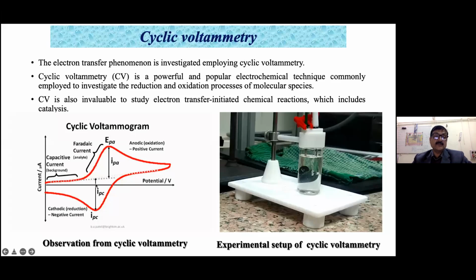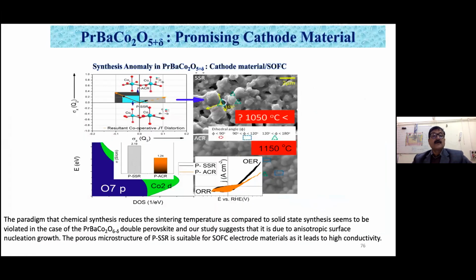There is a peak on the negative side, which is the cathodic reaction. This is the anodic reaction, and this is connecting again. So this is a kind of duck shape characteristic that is observed. This is a result from our lab, where we use PrBaCo2O5 material, where we prepare the system in 2 ways. One is through the solid state reaction, and one is through the combustion reaction.